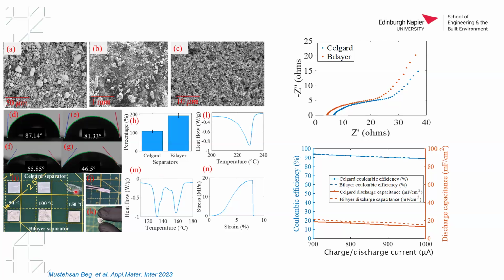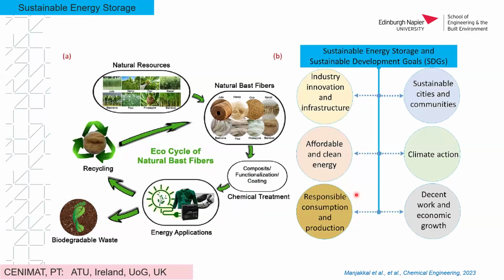So based on this separator, we fabricated the electrochemical capacitor with Celgard and bilayer, and we found that due to the electrolyte uptake of the separator, which shows the electrolyte interaction with low resistance, and performance wise, our device shows a very good Coulombic efficiency and discharge. We published this recently in ACS Applied Materials and Interfaces. If you are looking for more green energy storage devices in a flexible version or a sustainable application, you can utilize cellulose or a high water content material as a separator. Okay. In addition, there is another opportunity where you can develop green energy storage in a flexible version by utilizing our natural resources.